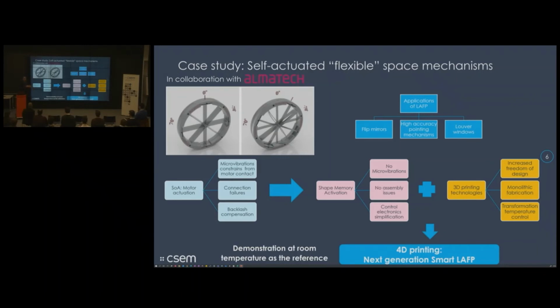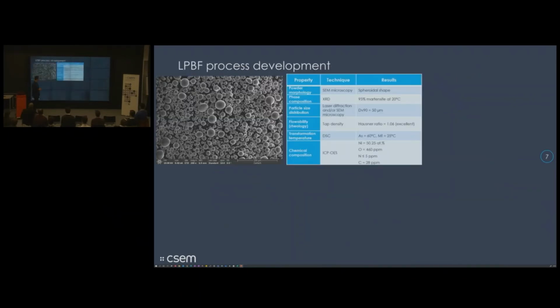So this is important because then you have to choose the right transformation temperature. But basically, depending on what your reference temperature is, your transformation temperatures should be taken into account. So first, we need to have the right feedstock material. In the laser powder bed fusion process, we work with microscopic powder material.